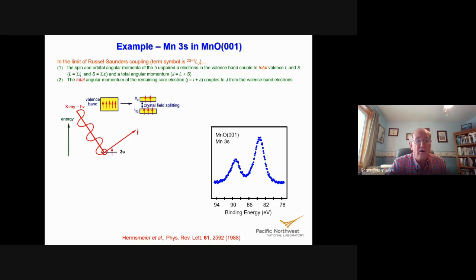So when we then think about the photoemission piece of it, the total angular momentum of the entire system, the ion after photoemitting from the core, is going to be the angular momentum of the remaining core electron coupled to the total angular momentum of the valence electrons. So it turns out that if you have a high spin crystal field split ground state for an octahedral coordination like this, there's only one way to couple those 5 unpaired electrons, and the term symbol is sextet S, 6S.